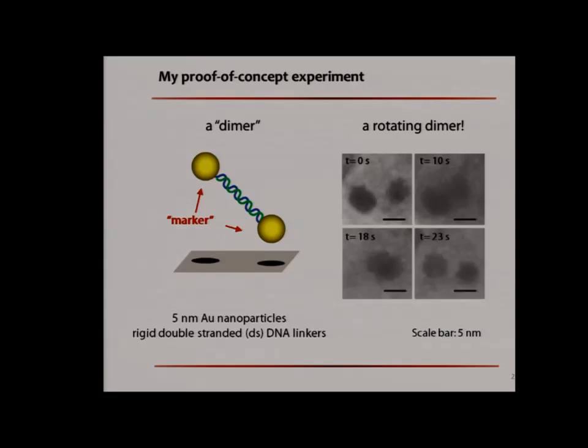And then let's look at the images. You can see two dark circular shapes. Those are the projections of the gold nanoparticles. You can see the distance between the projections is changing. At one moment, the two projections even overlap with each other and then become separated again. And that can only be possible if we have two particles rotating as a dimer in 3 dimensions. So we do have motion in 3 dimensions.